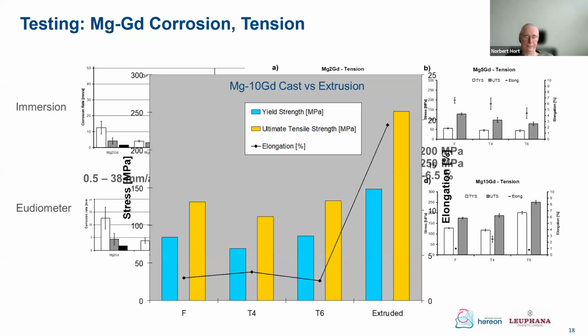And when processing, this was also emphasized before a bit, look at the processes. When you look for cast materials, the stress will not be as high as you can get from an extruded material in this case. As an example for magnesium 10 gadolinium. So it's about composition and processing, and basically that's the microstructure.